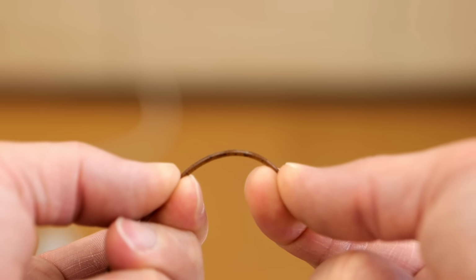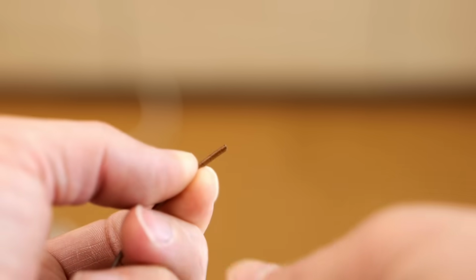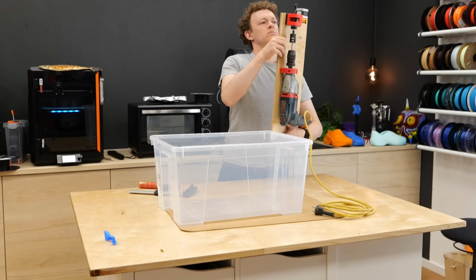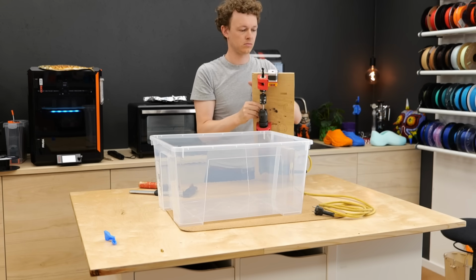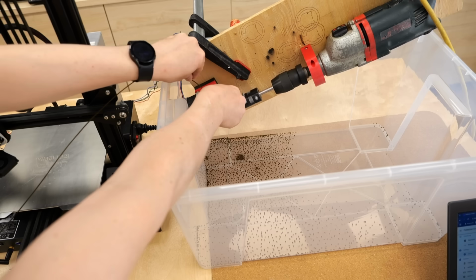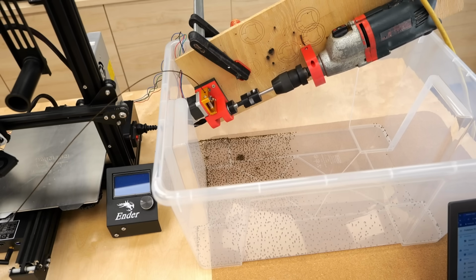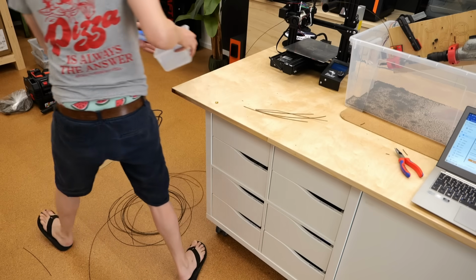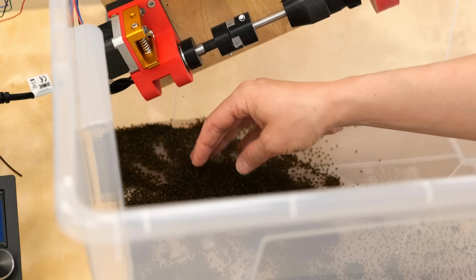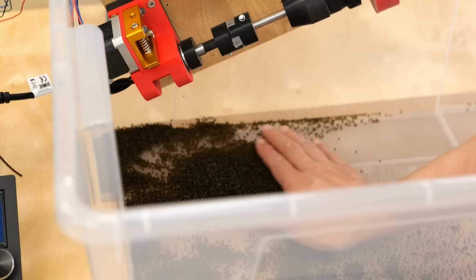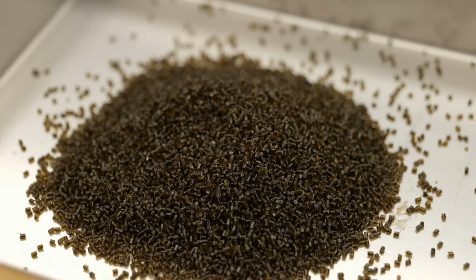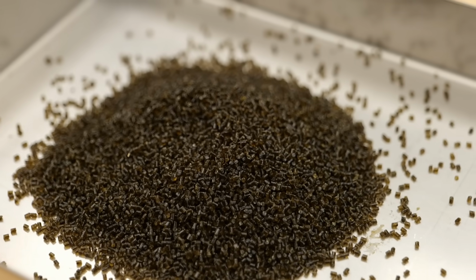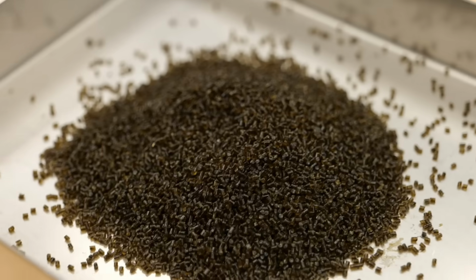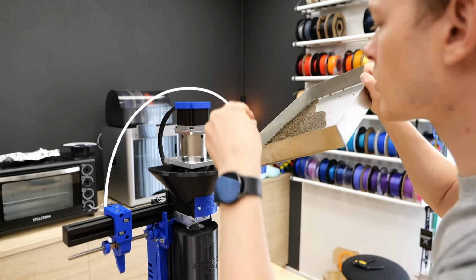The idea here was that this should not only make the distribution of the material more equal, but as I hoped, it would also break up the agglomerations and distribute them as well. So I got my old filament pelletizer, which is basically a wood drill into which I feed my filament at the right speed so that I pelletize the material. I gathered all the filament chunks I had previously made and chopped them up one by one, which took a bit of time, but in the end I was left with a good amount of pure PLA pellets to process further. I put everything in the oven again for a few hours to drive the moisture out and then poured it all into the hopper for a second round of extrusion.